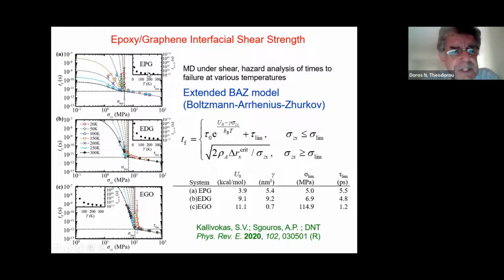We have results for the pristine graphene, the defective graphene, and the graphene oxide. This is the time to failure of the interface as a function of the imposed force or shear stress, sigma zx, for a variety of temperatures. The higher the temperature, the shorter, of course, the time to failure. Now, one observes several things in the output of these simulations. When the stress is higher than a certain limiting value, which we call sigma limit here, one sees that the results for all the temperatures collapse onto a line in this log-log plot, which has a slope of -1/2.